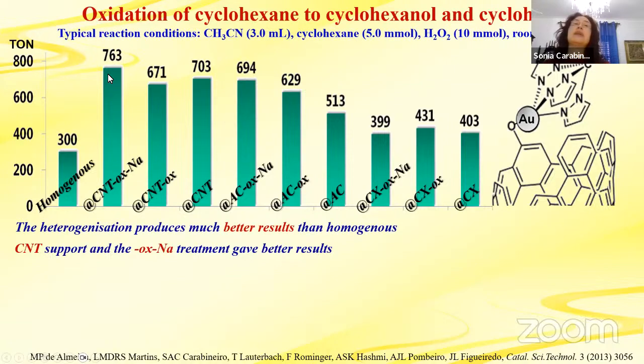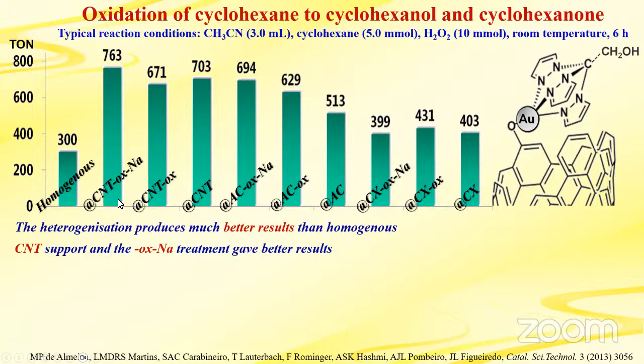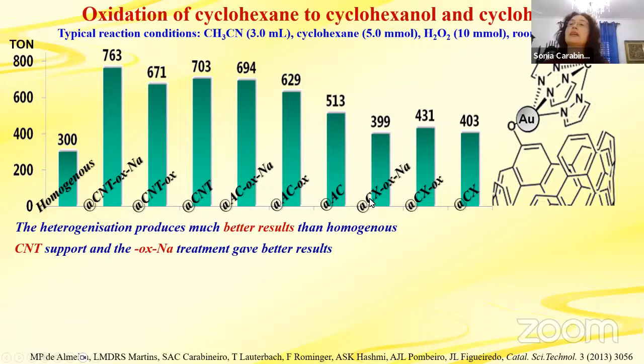And we see that carbon nanotubes here produce the best results, and also this treatment with nitric acid and with sodium hydroxide. So these ones, the ox-Na, have better results, not only here on carbon nanotubes, but also on activated carbon.